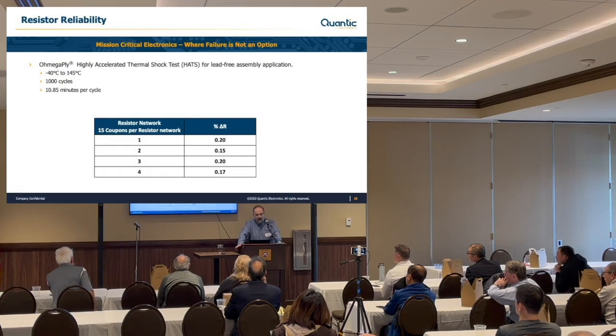And then we've done HATS testing at lead-free assembly conditions, and again, thousands of cycles, 10.85 minutes per cycle, and we had 15 coupons per resistor network, and you get a very small change in resistor values. It's very stable.